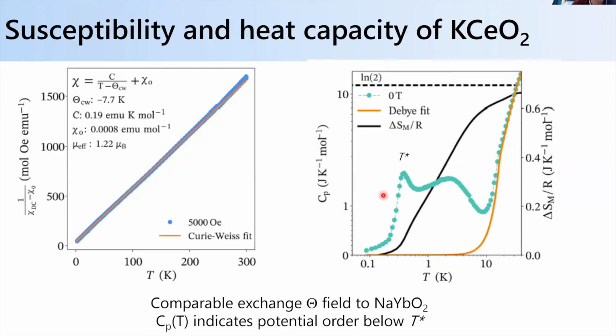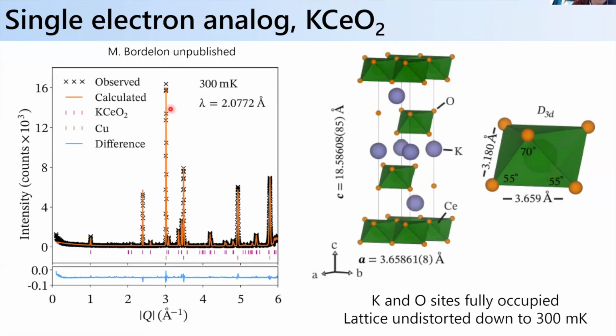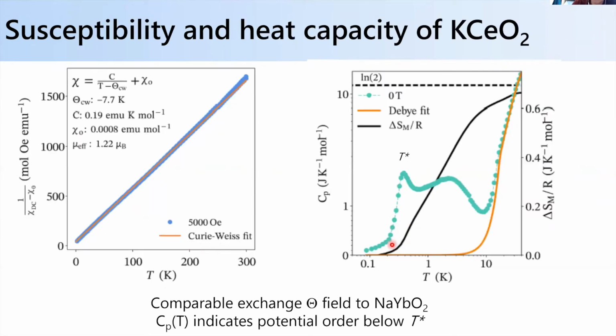Okay, and what initially got us interested in this is, I'll go back one slide. This data was collected at 300 millikelvin, and we actually don't see any magnetic Bragg peaks here. So, in principle, we were below this ordering transition temperature, and we weren't seeing magnetic Bragg peaks. So we're like, oh, what is this order? What's going on? That we're catching in heat capacity, but not in neutron scattering.